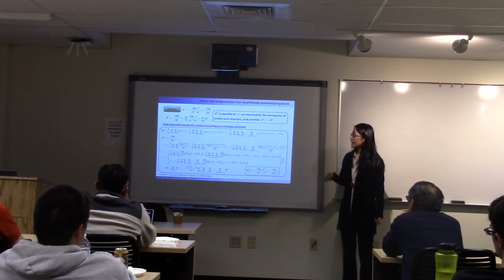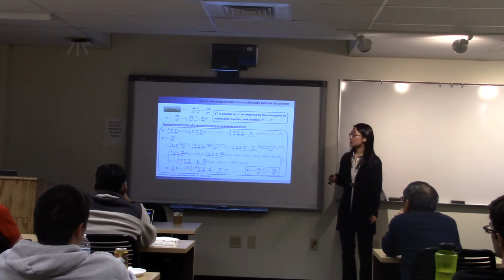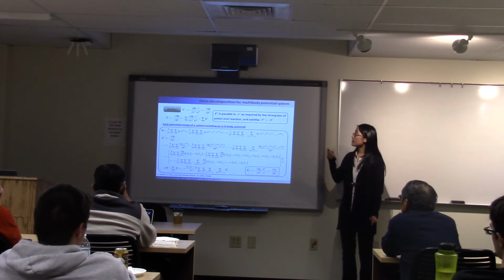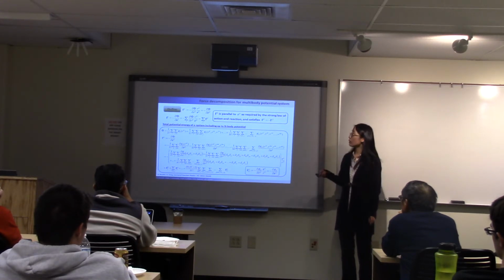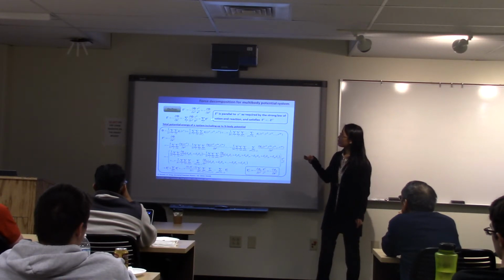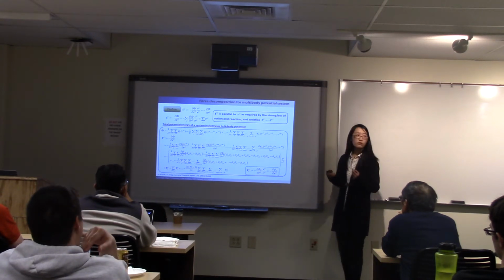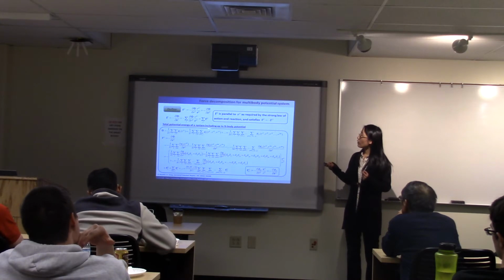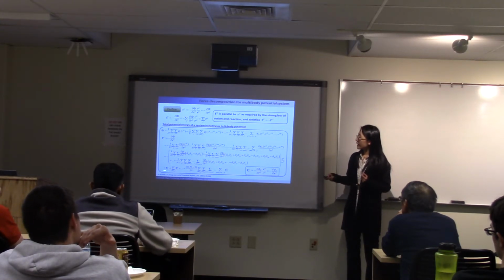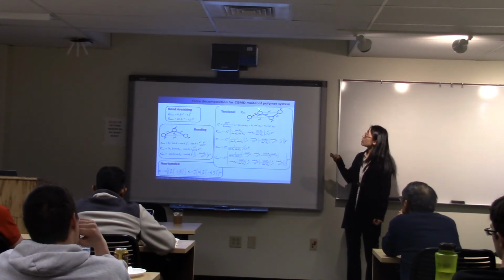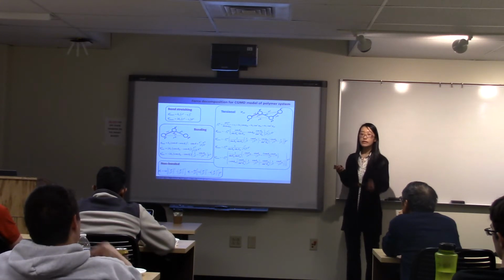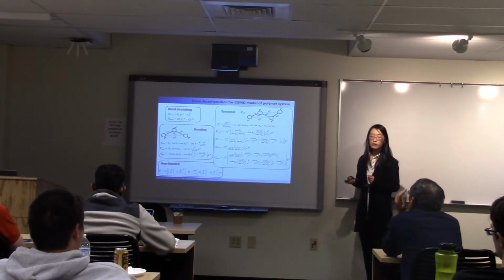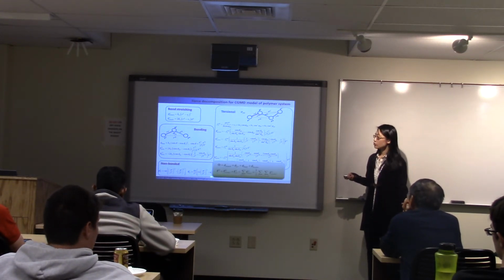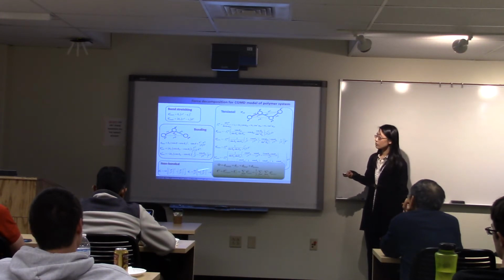But the limitation I mentioned in the Hardy theorem is that it was developed for the pair potential system, where this Fij is very straightforward. It means the force on atom i from atom j. But for a multi-body potential system, this is very problematic and not straightforward. So we propose that if we define Fij based on this expression, the assumption in the derivation of the Hardy theorem can be satisfied. For an n-body potential system, this Fij doesn't only have a contribution from the pair-body term, but also from the three-body up to the n-body term. More specifically, for a polymeric system, we have bond stretching and non-bonding terms, which are two-body terms, and the bending and torsional terms are three- and four-body terms. So in total, we have contributions from the stretch, non-bonding, bending potential, and also the torsional term for the Fij.